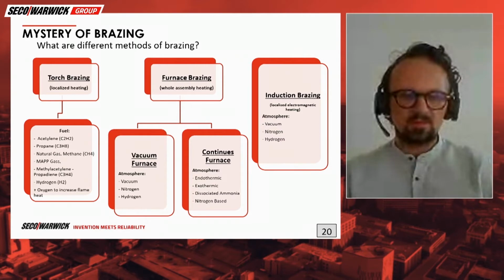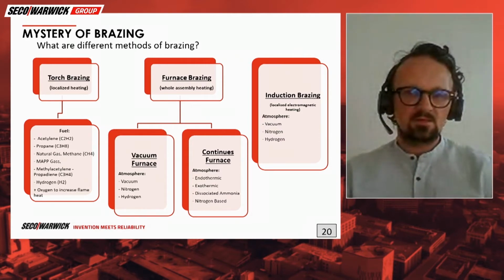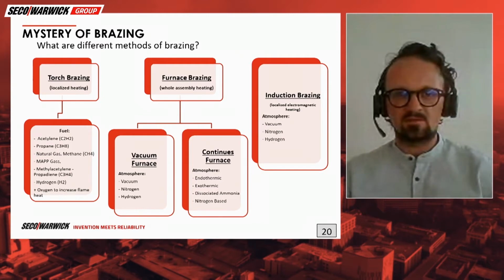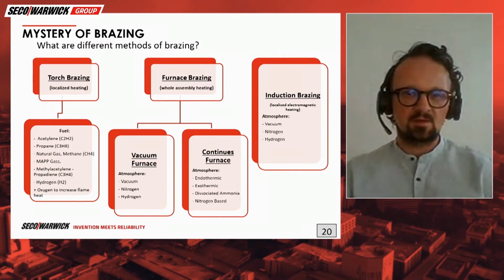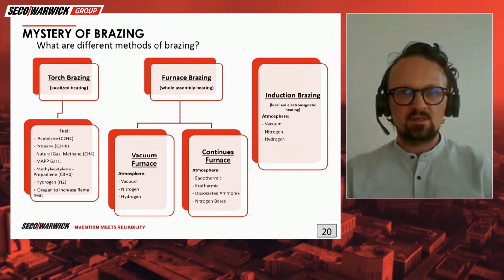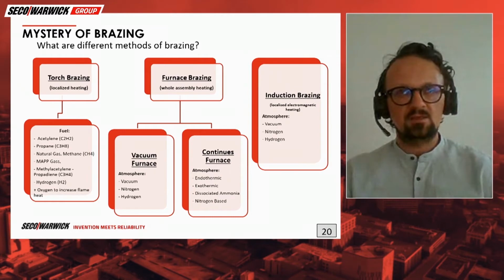For example, we can braze the parts in 10 seconds or even less, compared to torch brazing or furnace brazing. And you can combine it with different protective atmospheres. You can use a flux with it, or you can do it without flux. You can control the process a little bit better. But it has some drawbacks: induction is very localized heating, so the joint is never heated as uniformly as in the furnaces.